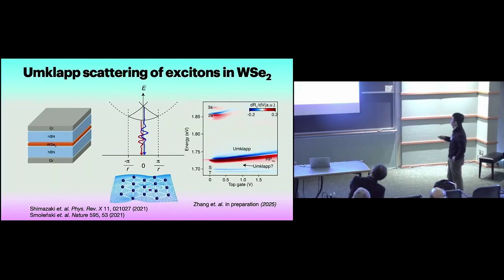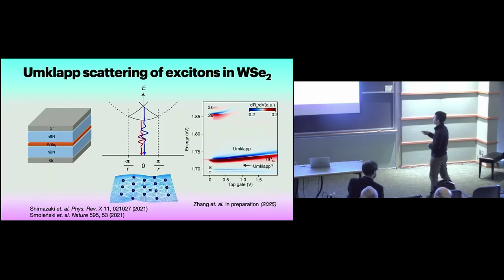As I increase the density, the interparticle distance becomes smaller, the pi over r becomes larger, so the energy difference between them becomes larger and larger, and we see a larger separation between the Umklapp and the repulsive polaron. This was very similar to what Tashi observed in monolayer MoSe2. And if you squint a little bit, we can see that not only for the repulsive polaron branch or the exciton branch, we also observe the Umklapp features for these attractive polaron branches. From this, we can potentially measure the effective mass of the repulsive polaron versus the attractive polaron. This is still something that we are trying to work on.